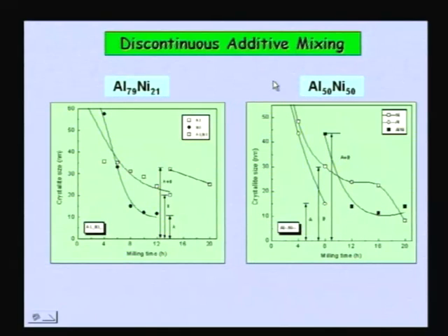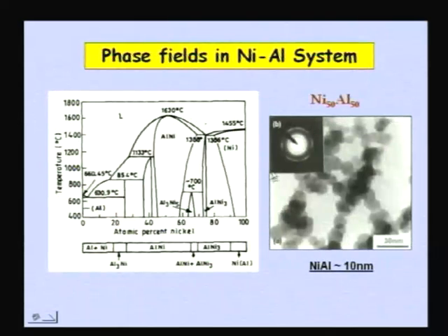So, this is another mode of alloying which occurs during mechanical alloying in case of ordered compounds, not for solid solutions, but in case of ordered compounds with high negative enthalpy of mixing, you get this kind of discontinuous additive mixing. And one can have extension of phase fields in the intermetallics also. We talked about extension of solid solubility in solid solutions, but one can have extension of solid solubility in intermetallics. For example, NiAl is one such example, where in equilibrium conditions you get a solubility from 45% to 55%. Here you can get from 25% to 65%, a very large extension, and it is all because of nanocrystals. And one can show that when you make it nanocrystal, the phase field becomes much larger. This is very easy to show.